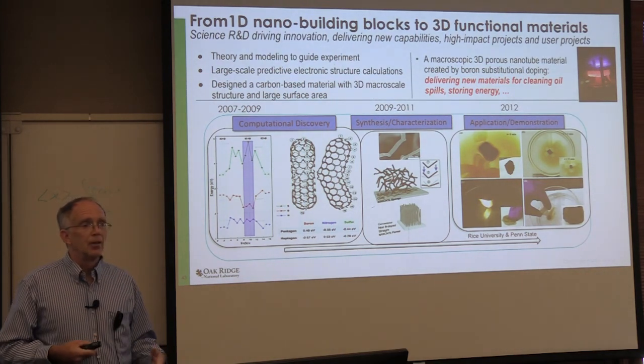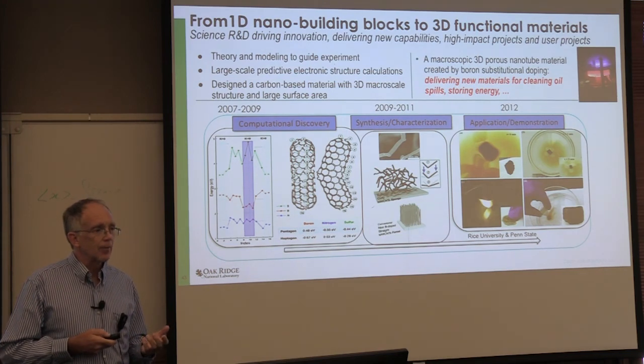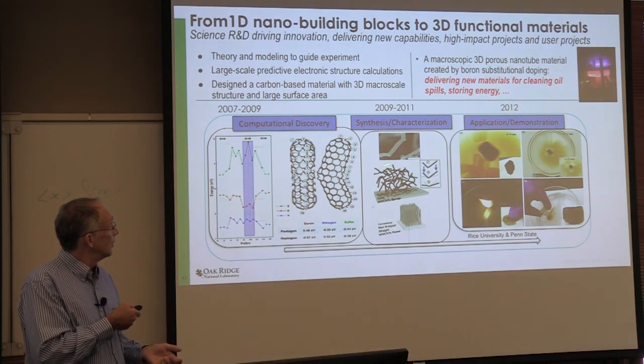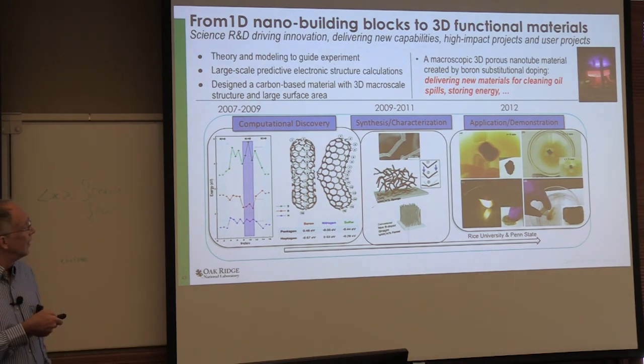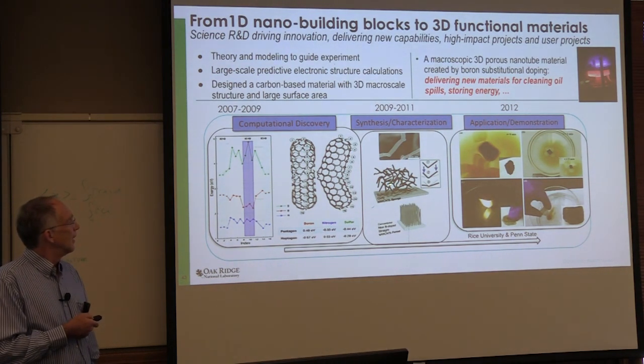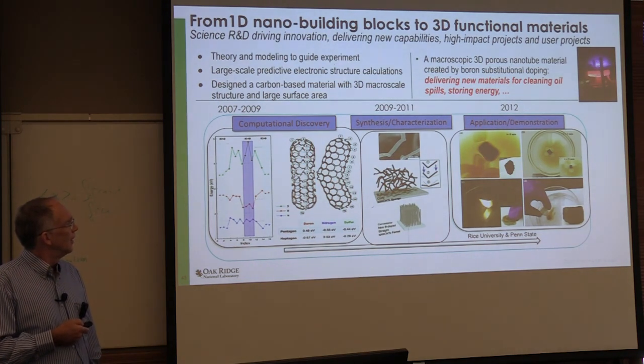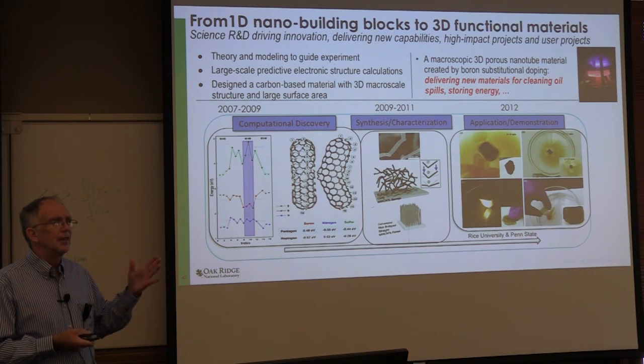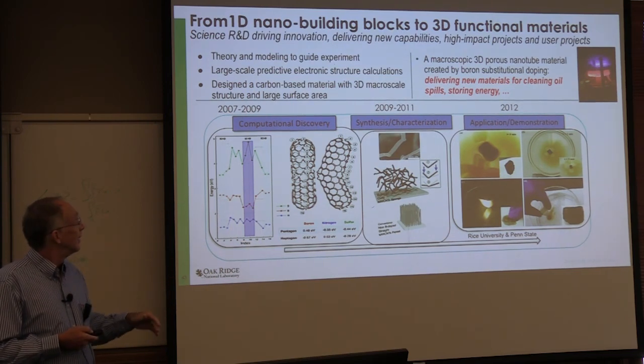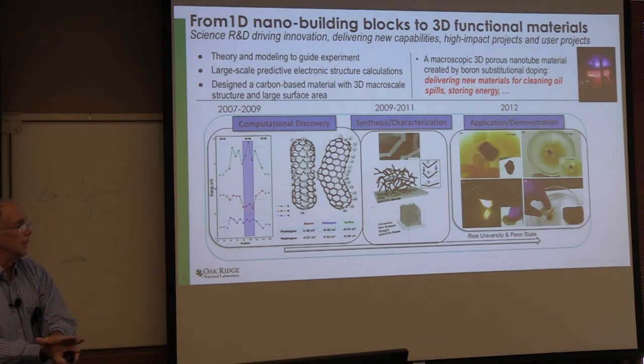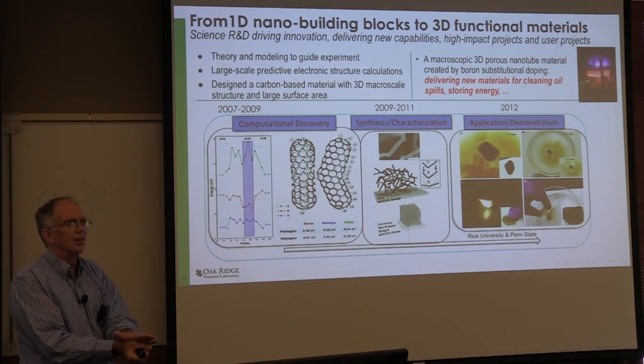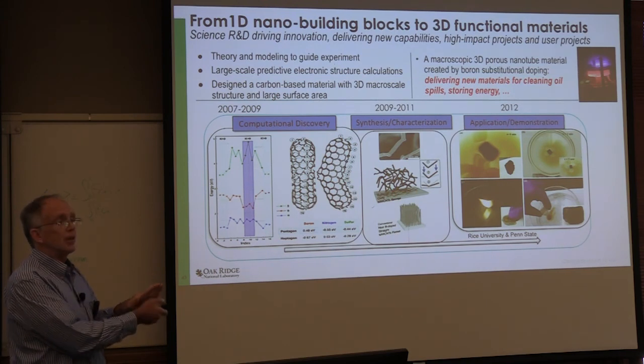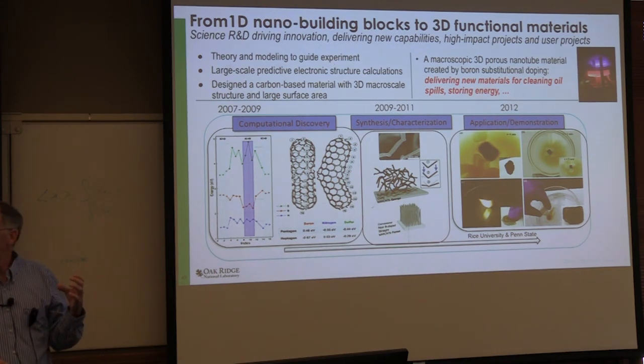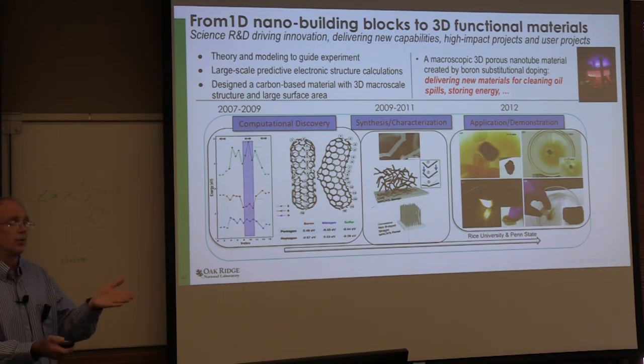So you can grow carbon nanotubes that are macroscopic in size. What's interesting in this entangled bundle of stuff is mostly it's just a bunch of air, right? It's about 90% air. So this is kind of an interesting skeletal structure that is mostly air. So it should have funky modulus, right? You should be able to squish that thing. And indeed, you can take that and flatten it out really nicely. Its modulus is really tiny. It's in a single Pascal level. And it'll return because the carbon nanotubes have a really robust mechanical structure. You can flatten it out a million times and it'll still return to its original size.